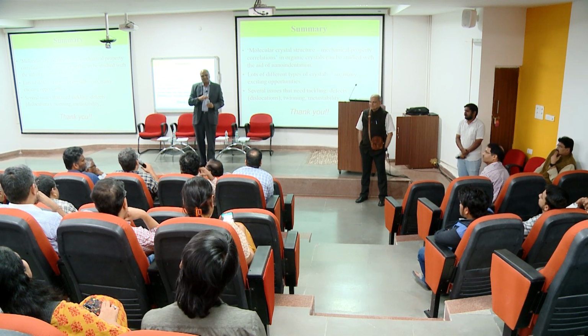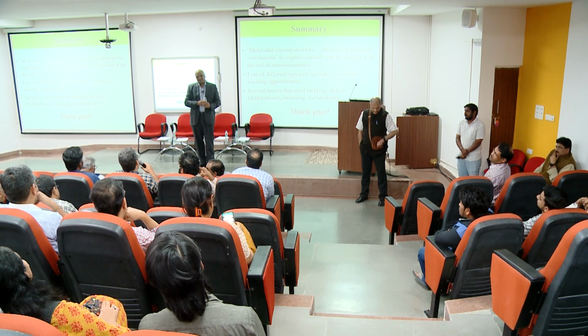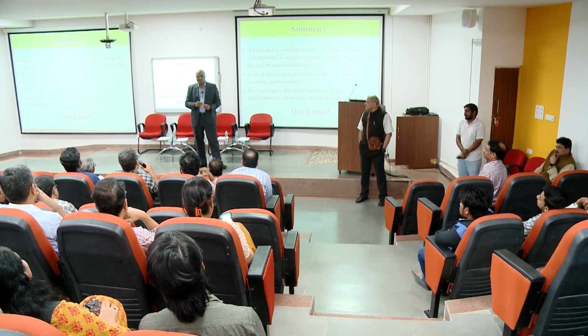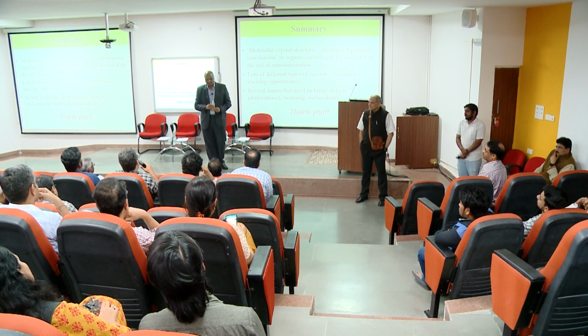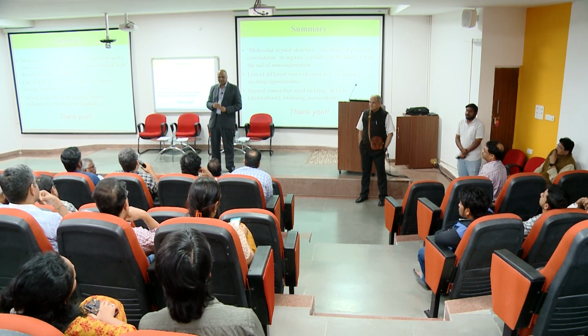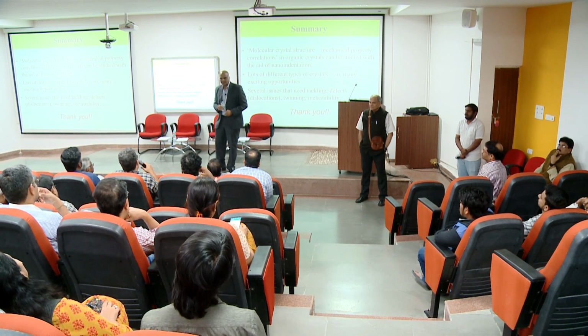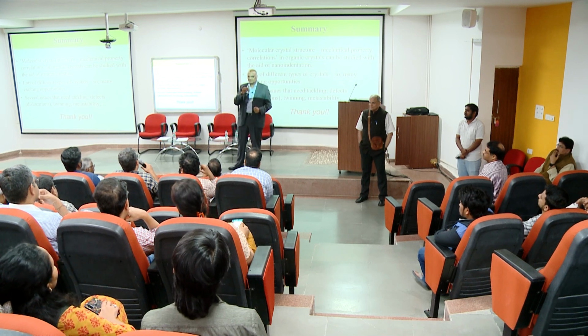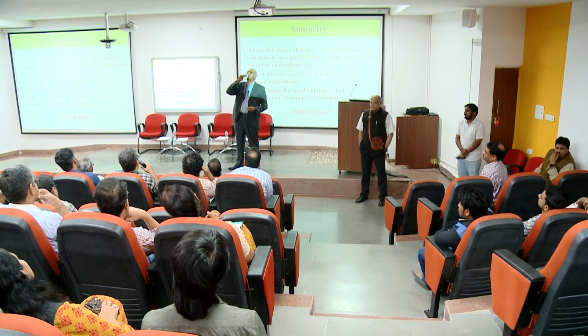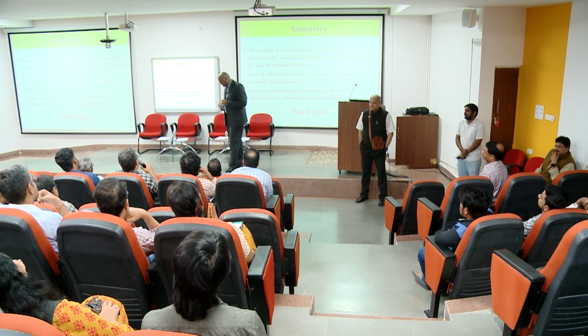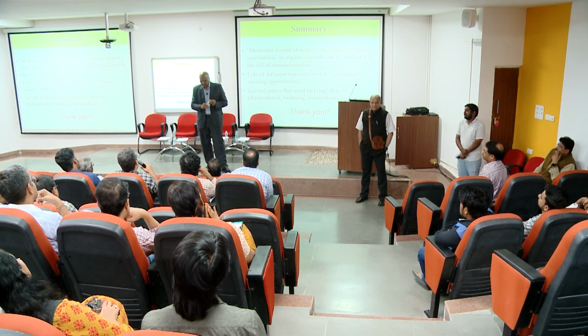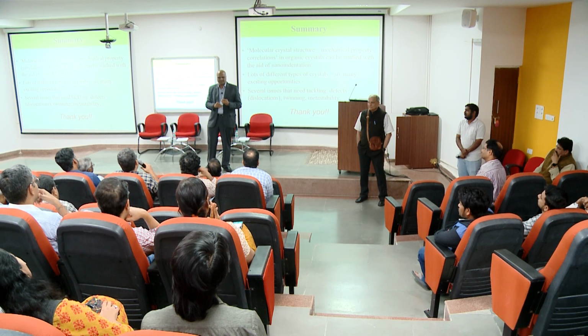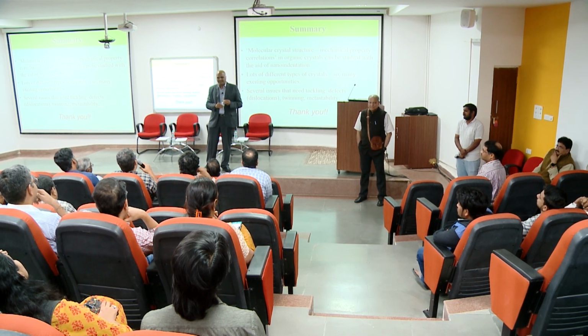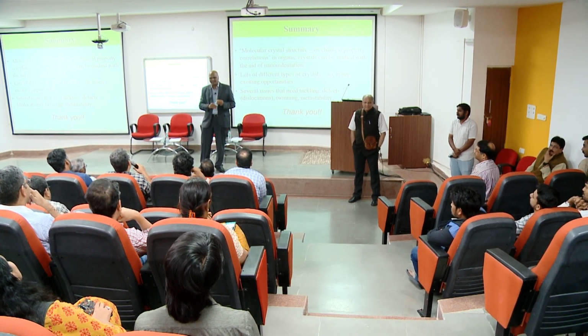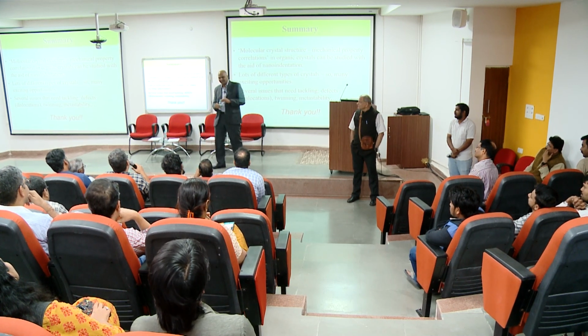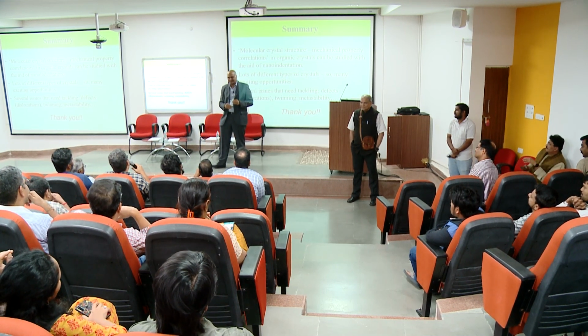So in such a case, have you seen any inelastic behavior in this? Oh, there will be plenty of inelastic behavior. Absolutely. Inelastic rate dependency will be there significantly. We looked at those aspects also. And how did the load dependent hardness go in these crystals? Have you got a chance to look at that? No, the indentation size effect is what you are referring to. No, we didn't do that. These are tiny crystals. We didn't really bother with that. You know that in metals we look at indentation size effect all the time, but not in this case.